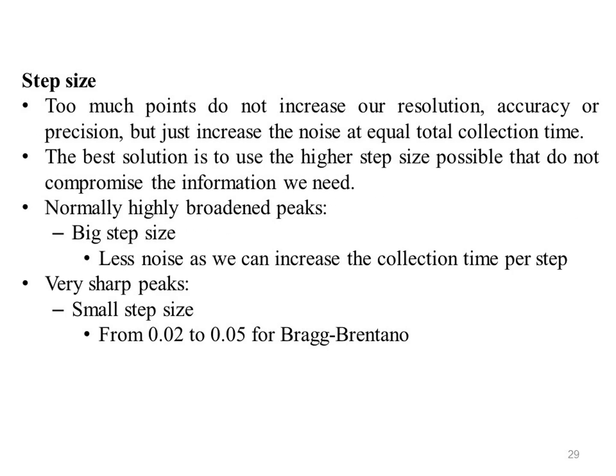The step size. The step size should be compatible with the line broadening characteristics and type of analysis. In general, 5 to 7 points in the upper half part of a peak are sufficient to define its shape. Slightly more points are preferred in case of severe overlapping. A little more for size-strain analysis. Too many points, too small a step size, do not increase our resolution, accuracy or precision, but just increase the noise at equal total collection time.